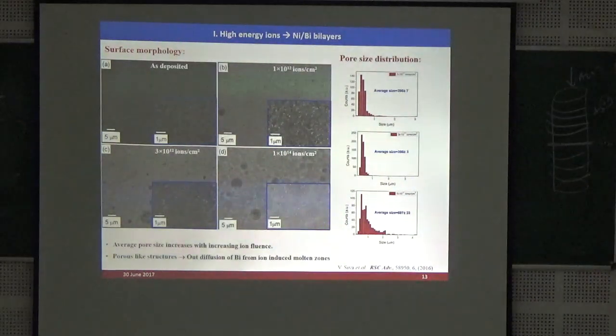So the surface morphology of the films can be seen here. As deposited, the film is very smooth, and after irradiation, at a fluence of 1E13 ions per centimeter square, you can see porous-like structures on the surface. With increasing ion fluence, we have estimated the distribution of these pores as a function of ion fluence, and it keeps on increasing. These porous structures are forming due to out-diffusion of bismuth. Along the ion track, you will have a molten-like zone. Since bismuth is a very volatile material, it is expected to go out from the surface. That is how we get this morphology.